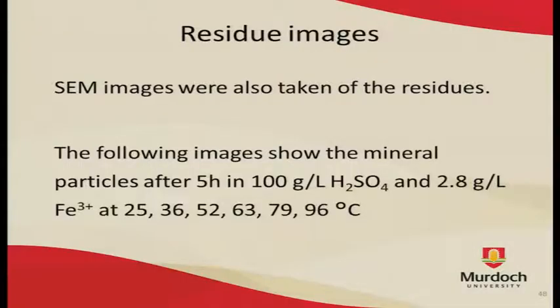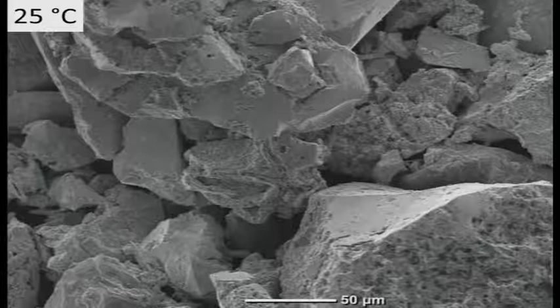In the next few images, I'll show the residue after 5 hours in 100 grams per litre sulfuric acid at progressively increasing temperature. Comparing these images, you can see the brannerite gradually becoming more and more corroded until it vanishes, replaced by something else in the end. Under fairly mild conditions, some of the faces of the mineral grains appear to have been attacked, whereas others are left intact. Not entirely sure why that's happening at this stage.